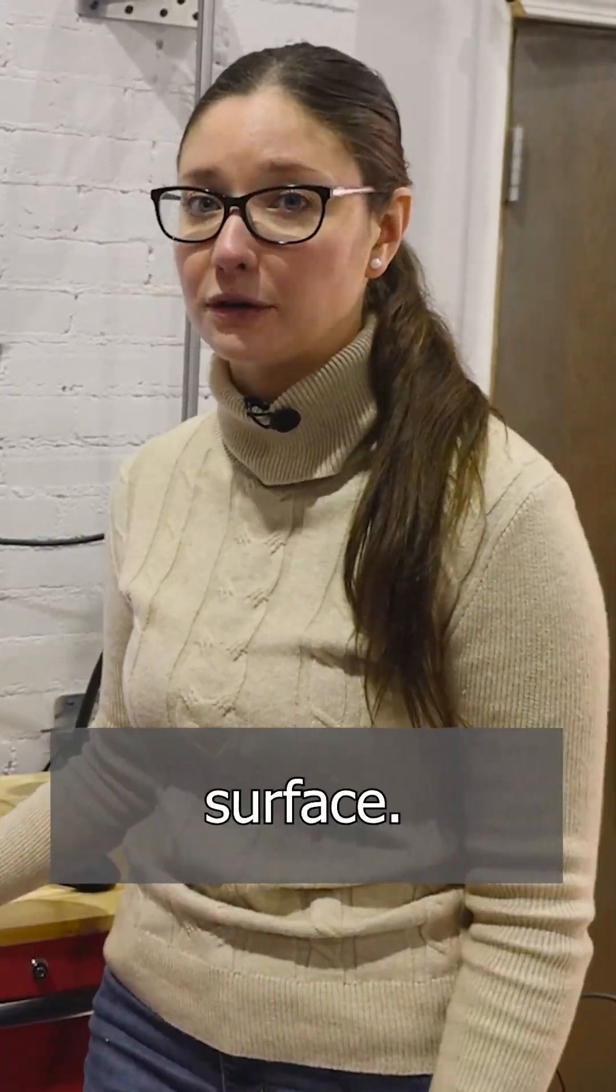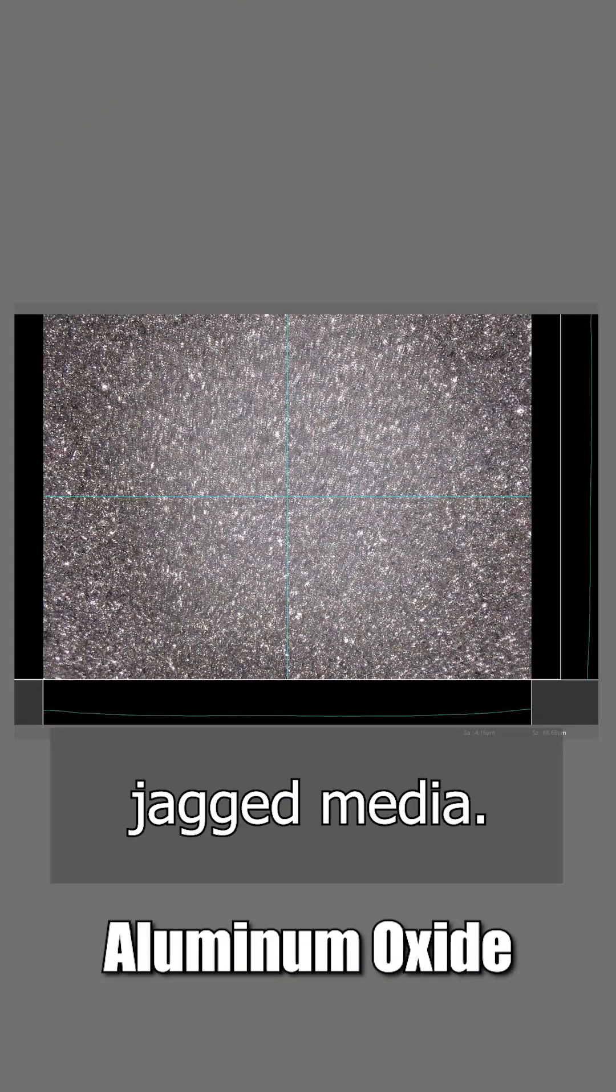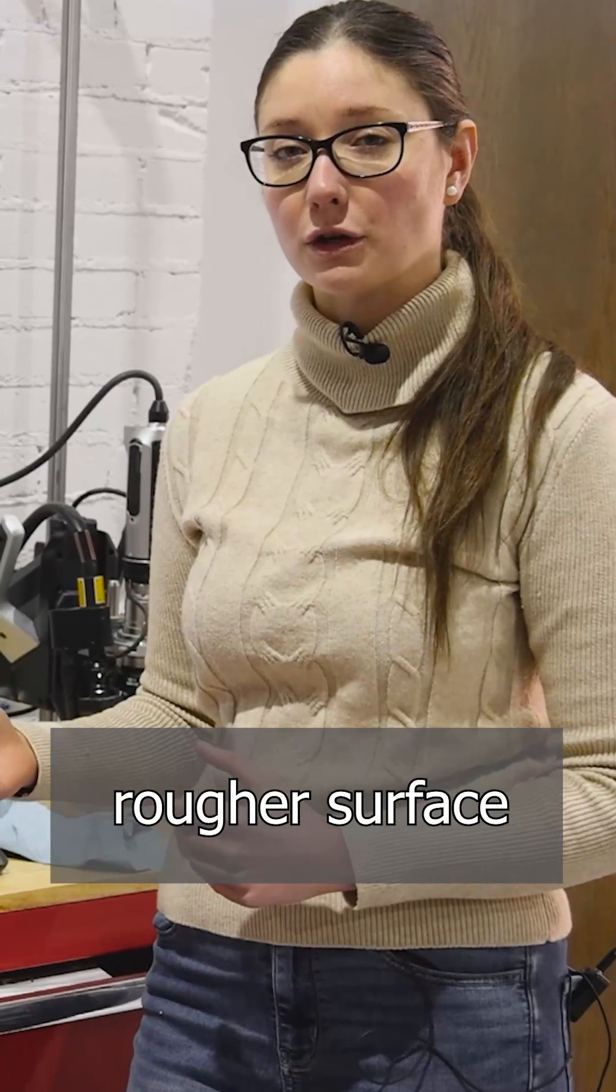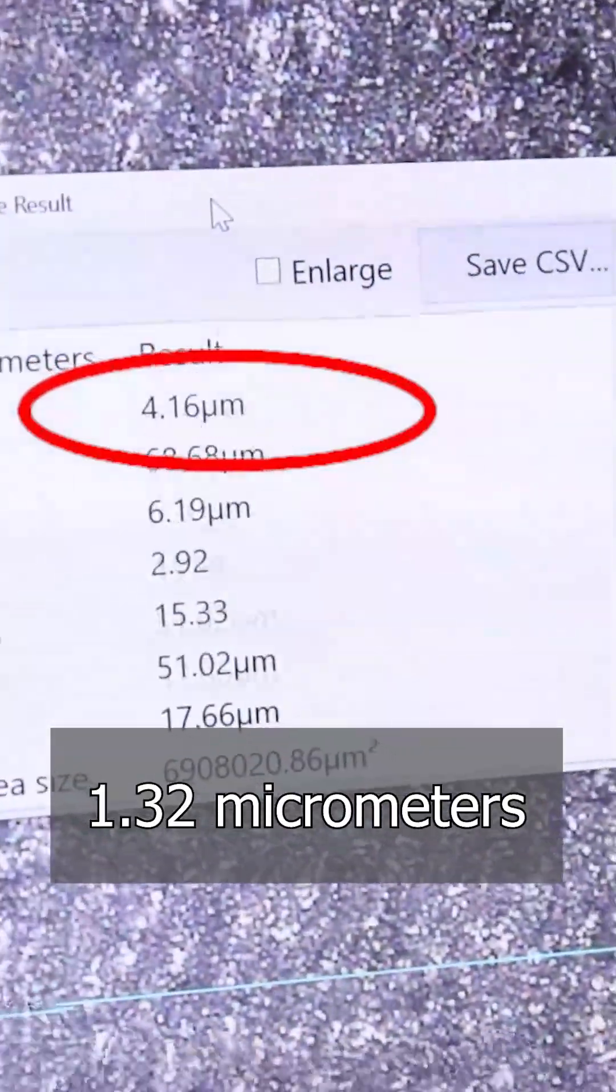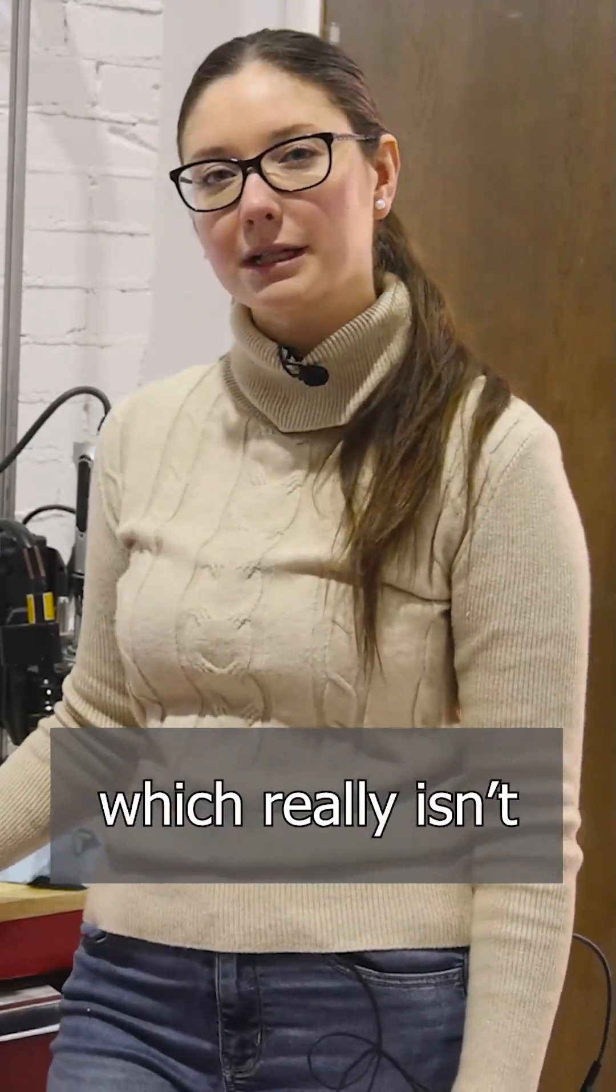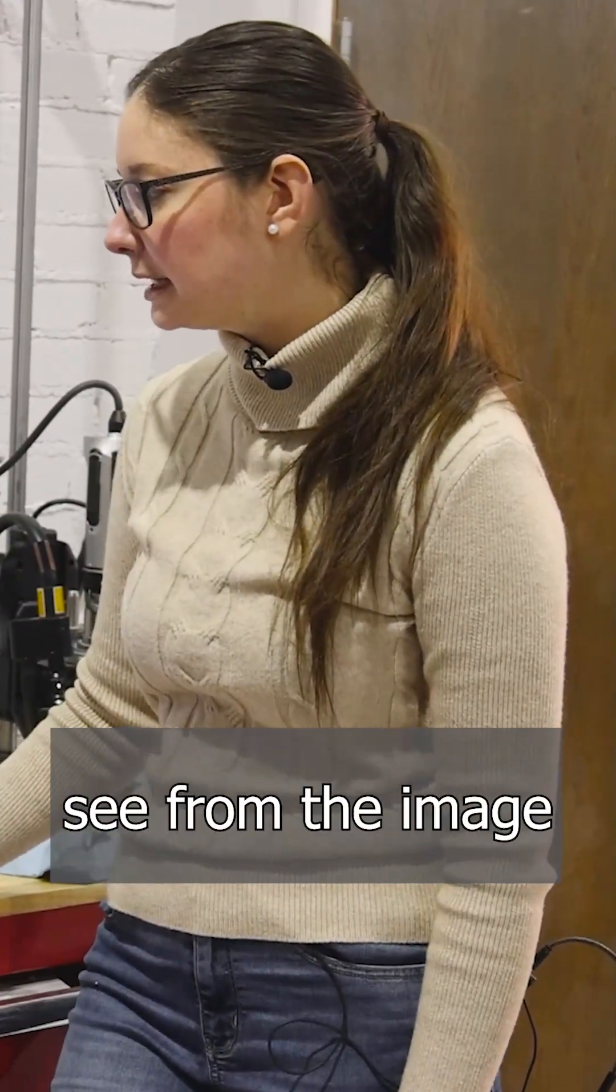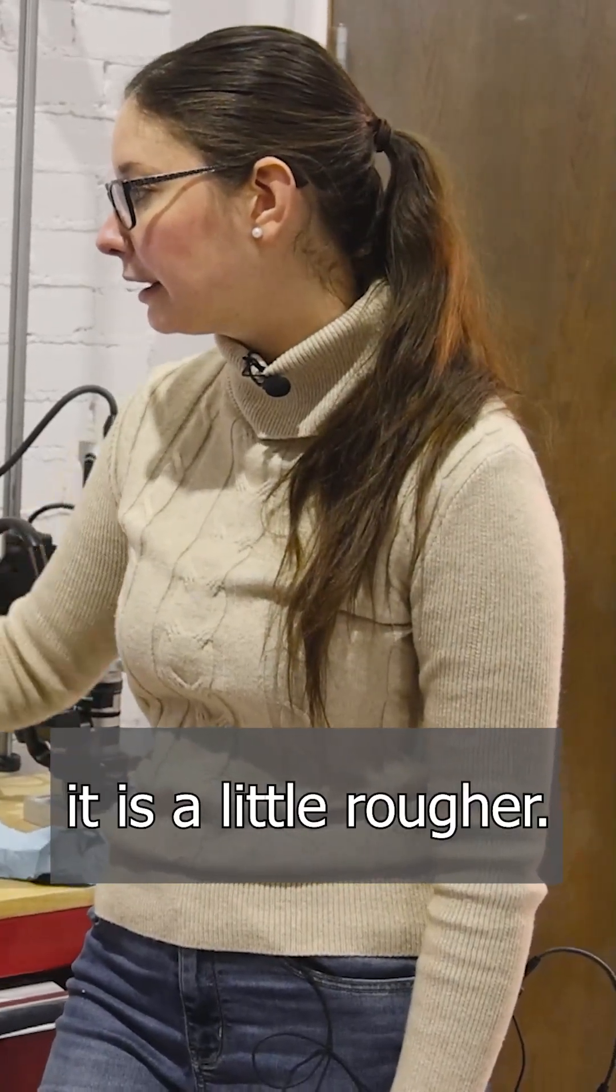Aluminum oxide is a solid, more jagged media, so it is going to leave a bit of a rougher surface roughness profile. We went up about 1.32 micrometers roughly in the surface roughness profile, which really isn't that bad, but you can really see from the image that it is a bit rougher. Still, we were able to get rid of those machine marks and leave a very smooth uniform profile.